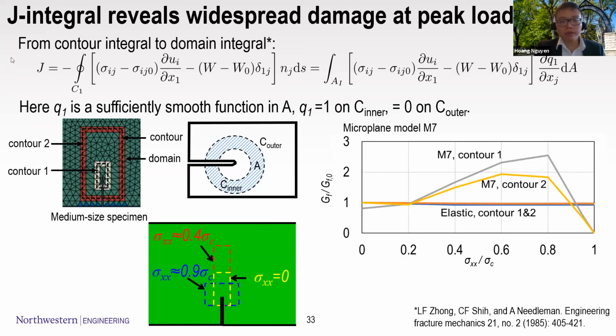So another source of confirmation comes from the J integral. We use the J integral together with the microplane model, and because this is a continuum model, we have to turn the J integral, which is a contour integral, into something that we can measure from the elements and that can be extracted conveniently from the finite element. Zhong, Shih, and Needleman offer such a method, and this relation can be derived using Green's theorem. After that we can extract the information from the J integral and the peak load.